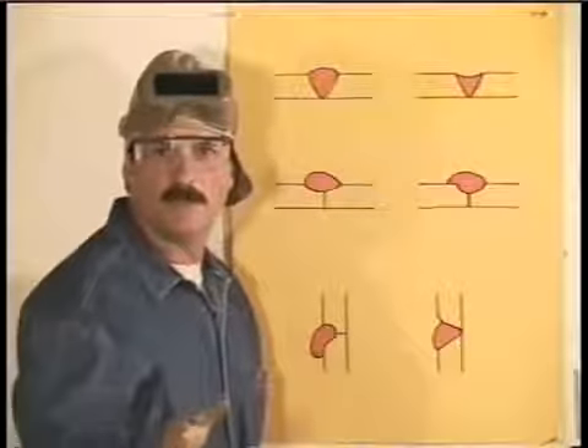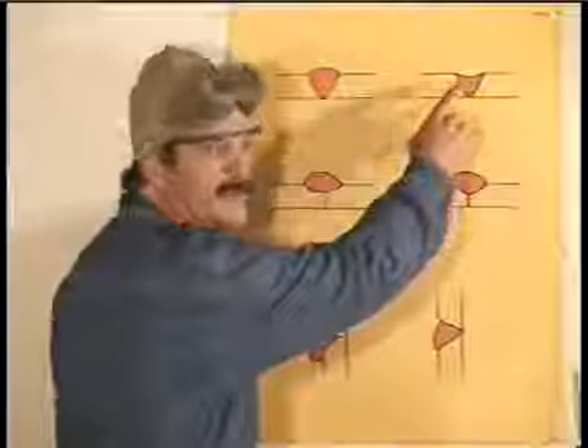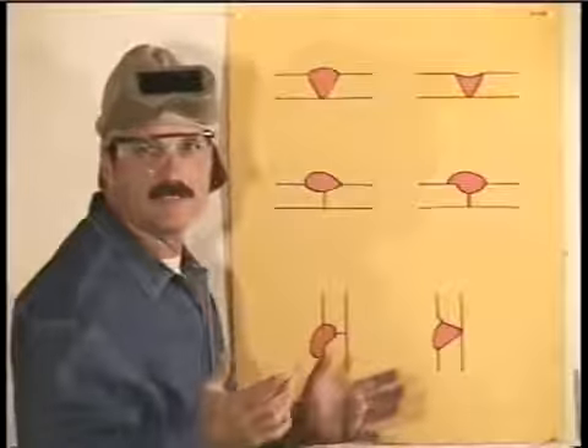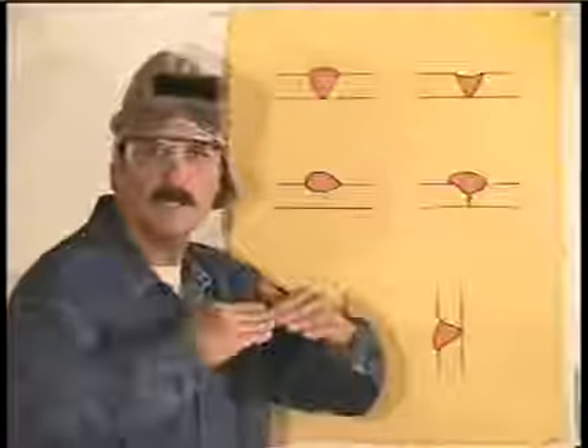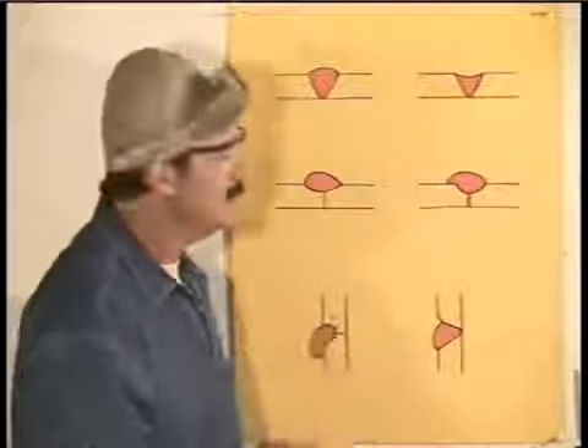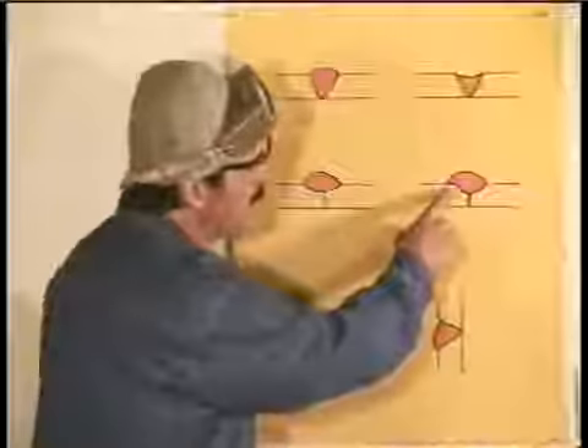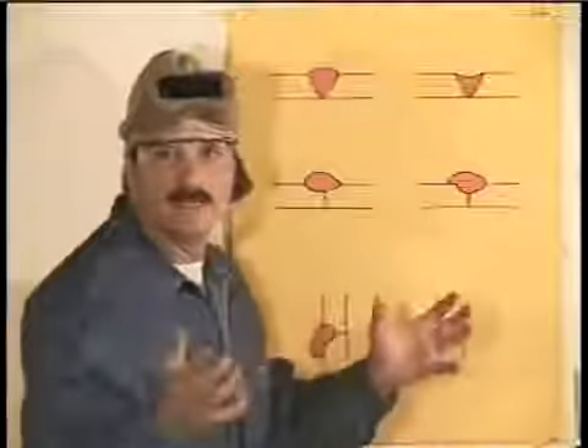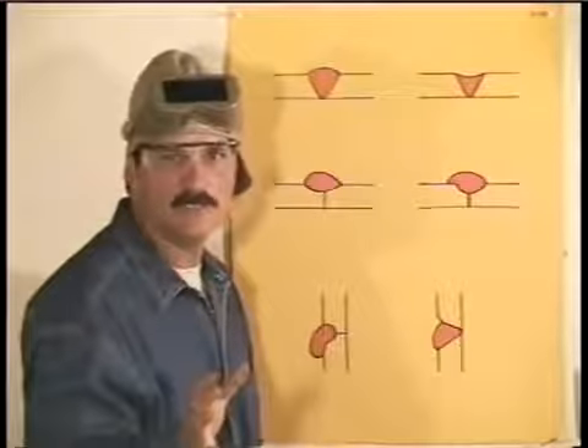If you don't run enough filler metal in, the weld may be below flush. And this can be fixed simply by cleaning it up with a brush and making another pass to build up weld bead. If you don't let the puddle penetrate enough, the metal will just lay on top. And if there's any kind of stress on this joint, it can work and it'll break. If the puddle's too cold or you're using too big of a rod and just gob some metal on, you can cold lap the weld bead. This part won't be tied in, and it doesn't do any good being there. It's also an indication that you didn't get good penetration.